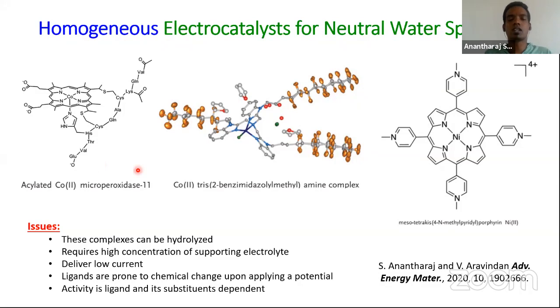But these catalysts have a few issues which are listed here, because we know from basic coordination chemistry that when we have water and apply potential, hydroxide can be generated in situ, and those hydroxides are capable of hydrolyzing this particular coordination complex. So they can undergo hydrolysis and deposit as hydroxide at the bottom of the cell and lose their activity. So this is one of the major disadvantages of this homogeneous electrocatalyst, where the electrocatalysts are basically coordination complexes.